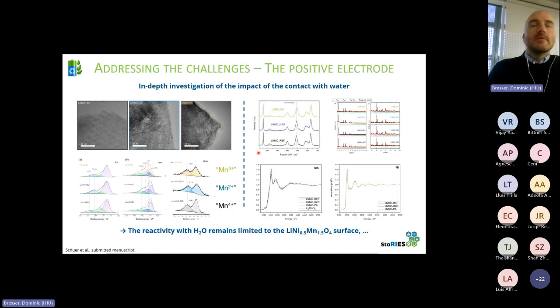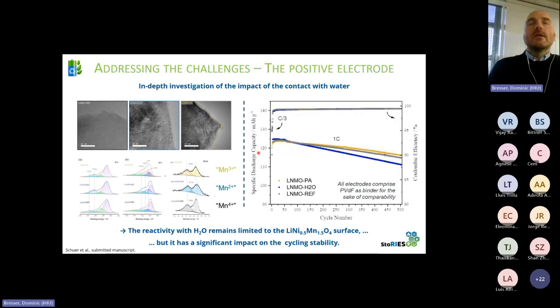In case the question went in that direction, you can get a similar or comparable result by, instead of treating the material with phosphoric acid and having the formation of this metal phosphate layer in situ, forming it artificially. You can, of course, also form a lithium phosphate layer or transition metal phosphate layer as such, in the absence of phosphoric acid, and those metal phosphate layers also have a beneficial effect. There's a bunch of papers showing this for the different phosphates, one working better than the other.